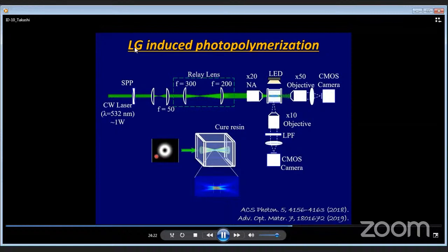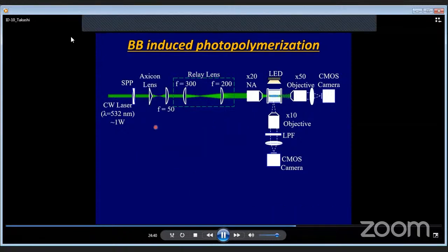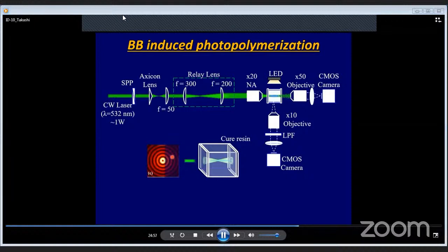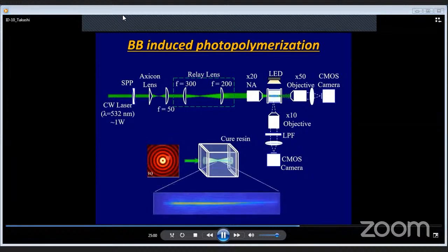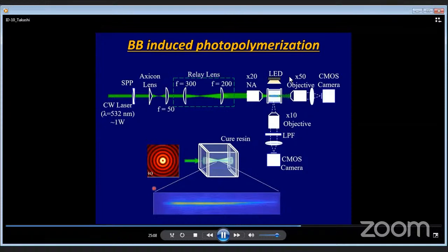Laguerre-Gaussian mode donut beam profile is injected inside the resin. The confocal length of the Laguerre-Gaussian mode inside the resin is about 1 millimeter. This is the diffraction effect. In order to convert the Laguerre-Gaussian mode into the Bessel beam, we introduce an optical axicon. Experimental setup is absolutely the same, just introduction of the axicon. At that moment, Bessel beam with multiple ring profile is injected inside the resin. Of course, Bessel beam exhibits non-diffraction effect. Confocal length is extended roughly a couple of millimeters. Which is better?